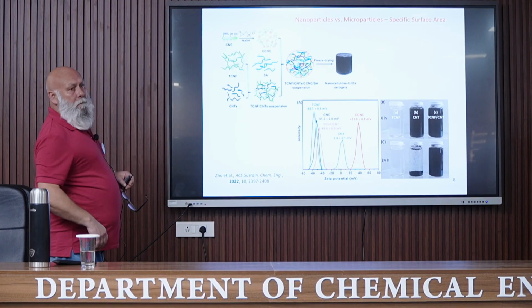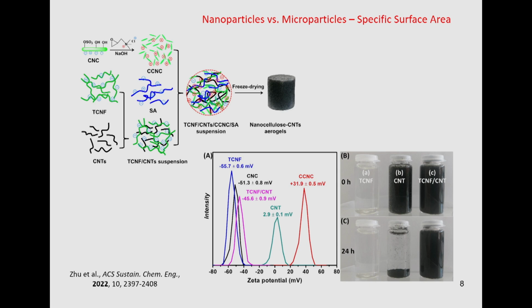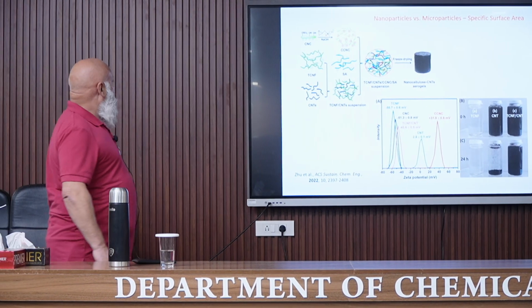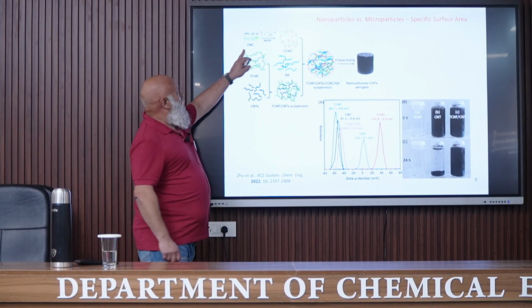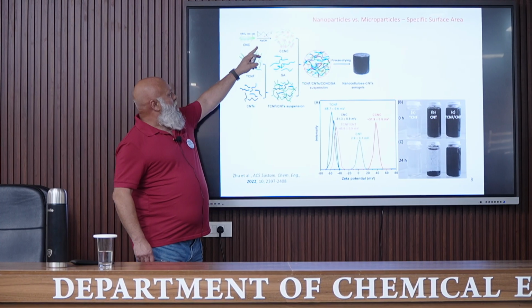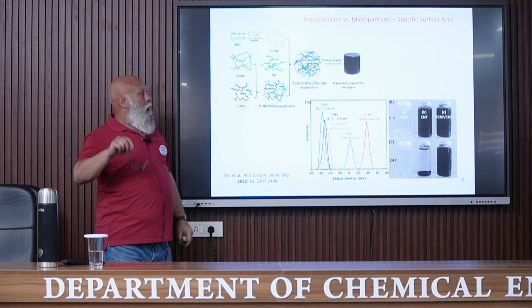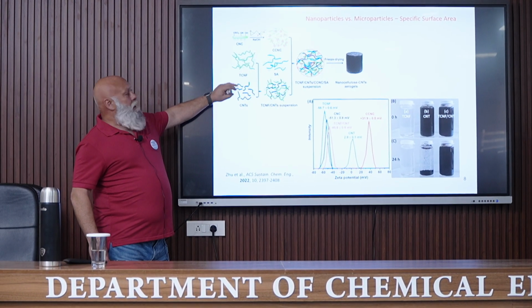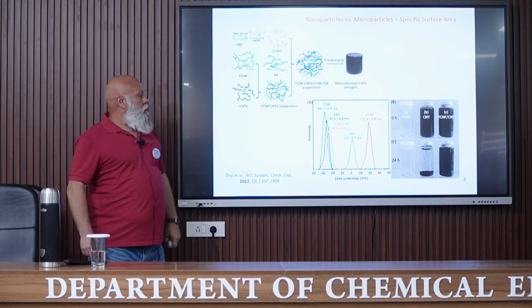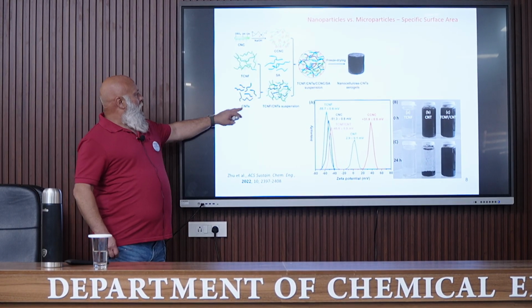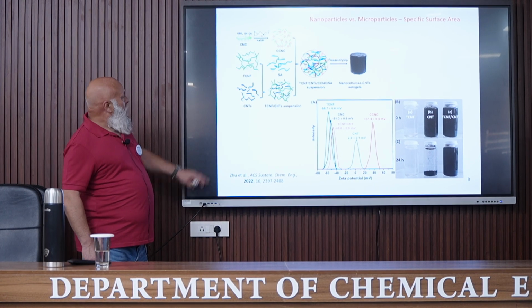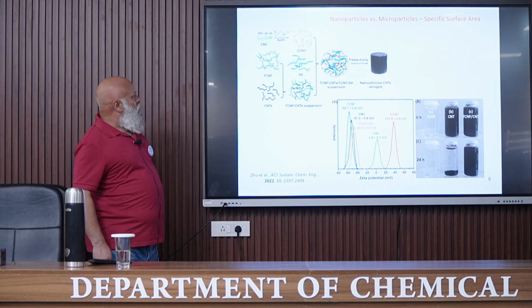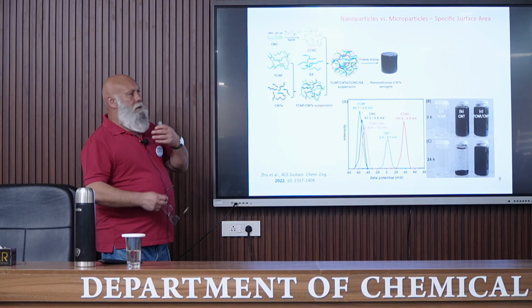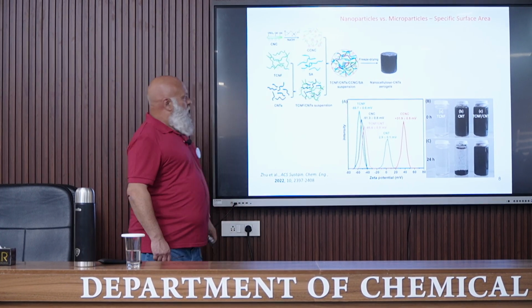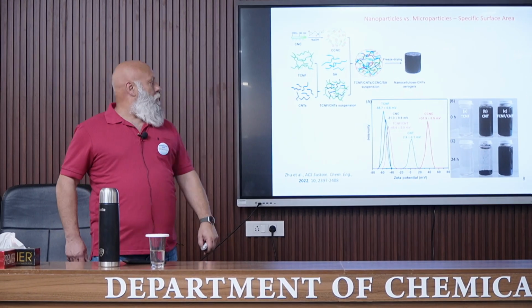Yes, so this is another application of the cryogel. It was performed quite recently by one of my Chinese PhD students. So first, he used cellulose nanocrystals, and these cellulose nanocrystals have been cationized to have a positive charge. He also used TEMPO-oxidized nanofibrils with negative charge, and so we'll have some interaction, of course, and carbon nanotubes. And he also used sodium alginate, which is negatively charged. And he mixed these different elements, and then by freeze drying, he can obtain an aerogel that contains all these elements.